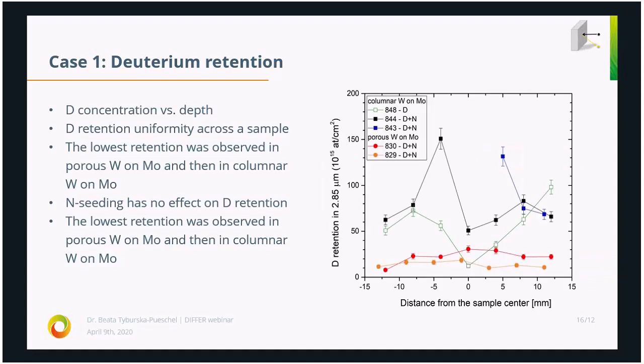And thanks to the fact that I was able to collect so much data, as I said, I can also see the uniformity of deuterium retention across the samples. So this you can see on this plot. Here we have deuterium retention up to maximum almost 3 micrometers, which was the penetration depth of the beam for that experiment. And here we have the distance from the sample center, and again, more or less 7 data points per sample. And here, for example, you can easily see that for the porous samples, the deuterium retention is more or less uniform across the entire sample.